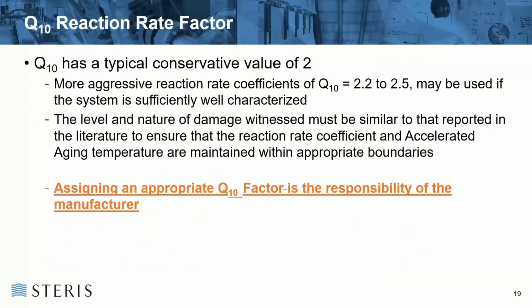Typically, the Q10 value is set to 2 as a conservative level for medical devices, and it's what the majority of companies use. If you want to move outside that, you're going to have to justify it, and you have to justify it by showing that the product and the packaging has not been degraded, in significantly greater detail than it would be in normal aging. And the level and nature of the damage witnessed must be similar to that reported in literature to ensure the reaction coefficient and accelerated aging temperatures are maintained. Again, the assigning of an appropriate Q10 factor is the responsibility of the manufacturer, not me, not the lab.